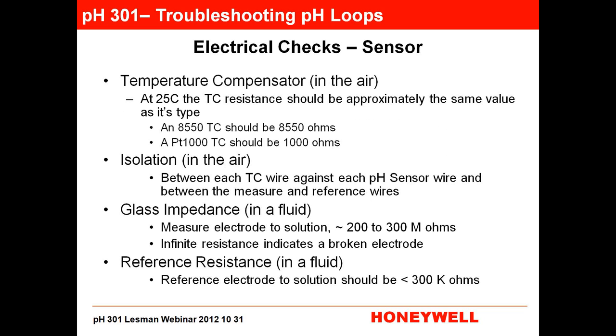There are some electrical checks that you can do on your sensor to find out what the problem might be. If you're having a temperature compensation issue, if it doesn't look like it's reading the temperature correctly, and you've tried a calibration on the temperature compensator, and most modern instruments will allow you to do that, then you need to check the TC, because usually with a temperature compensator, it's either pretty accurate or it just goes completely haywire, like you get the temperature of the sun or something. It's just a crazy temperature. But what can be the problem is you've got a TC in there and your instrument is not set up for that particular temperature compensator.